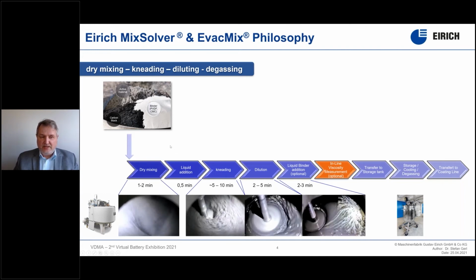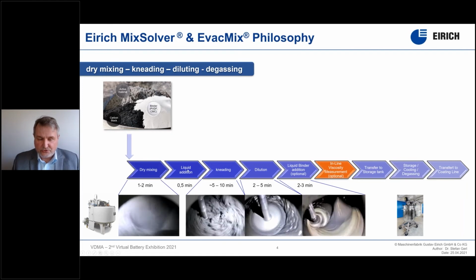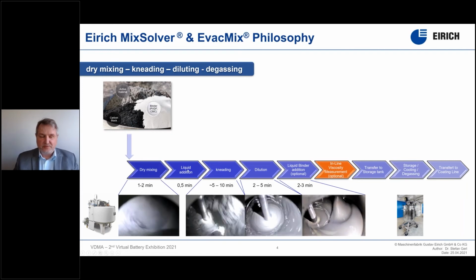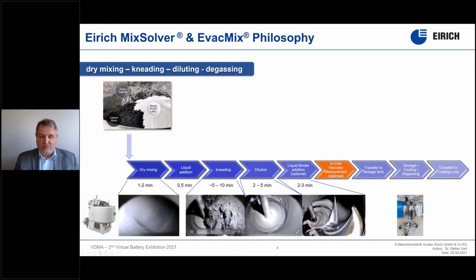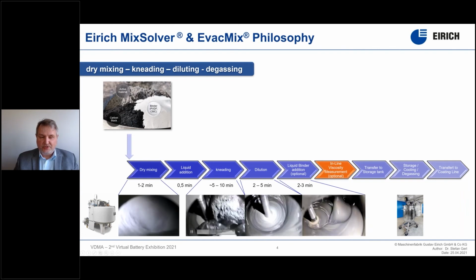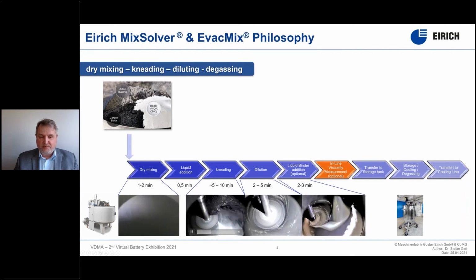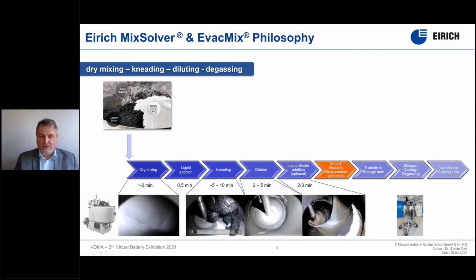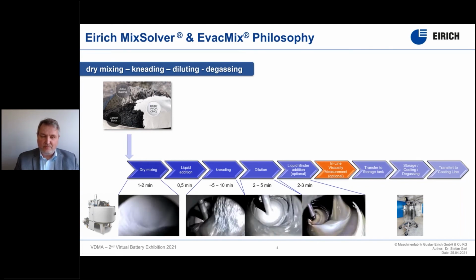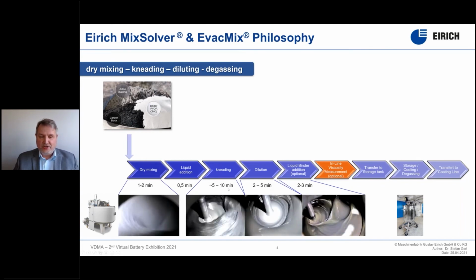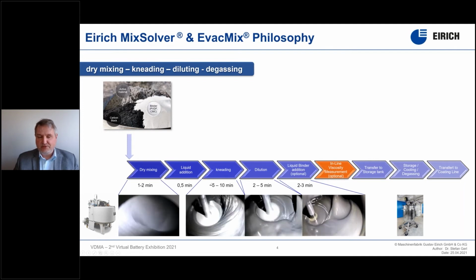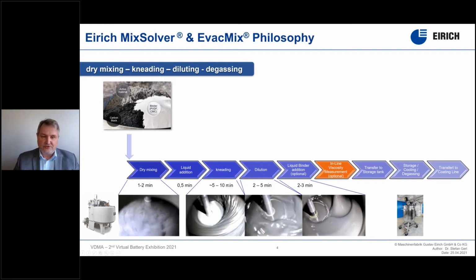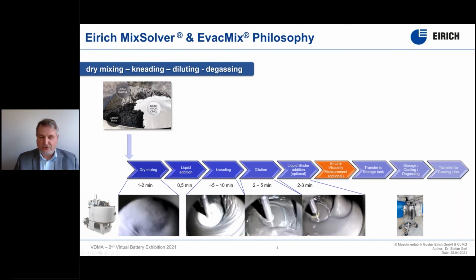Then we're adding very quickly a certain portion of liquid, which is usually 40–50% of the total. We are wetting the surface of the particles very efficiently inside of the machine, and then the binder starts to dissolve, and it will form a plastic body which can be sheared and kneaded over a period of roughly 5 to 10 minutes by experience. Of course, this can be prolonged and you can change the speeds and so the shear action.